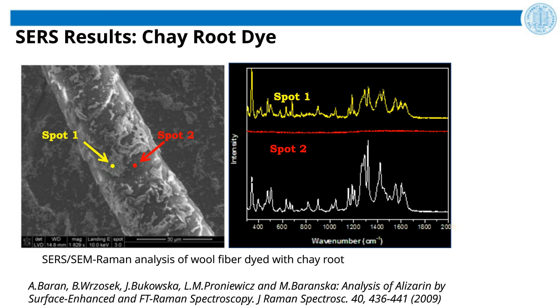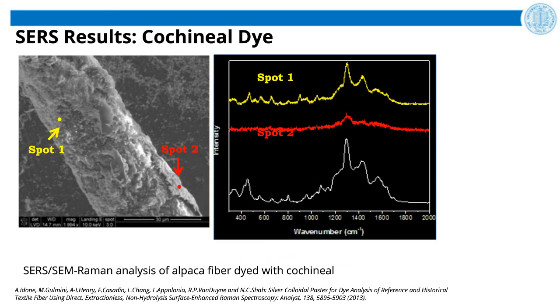This slide shows that sometimes the layer of nanoparticles can be thick or it can be detached. It also produces no Raman response. There is no signal, and only a uniform area provides good Raman response from the material. So this slide shows result of SERS analysis of alpaca fiber dyed with cochineal. The spectrum of the experimental sample shows characteristic bands similar to what is observed on the reference sample for carminic acid. And it is in agreement with published results for the SERS analysis of cochineal.